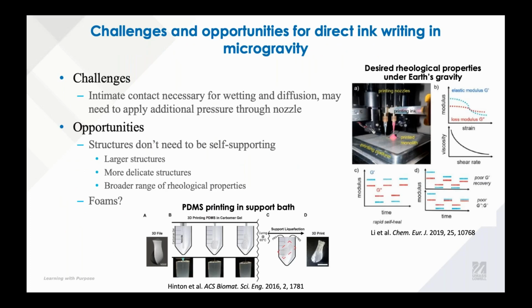However, in microgravity, we don't need to be worried about these structures being self-supporting. So again, there's this broader range. There's been a lot of work in coming up with desired rheological properties for these inks under Earth's gravity. You can see an example of this on the right of the screen. But when we don't need to worry about slumping, then we don't need to worry about having rapid recovery of our storage modulus, or about having an inappropriate ratio of our storage to our loss modulus quite as much. And so that really starts to broaden the range of materials that we could print. Potentially we can be printing things that on Earth we need to print and support. So things like PDMS could be printed freestanding. Next slide.